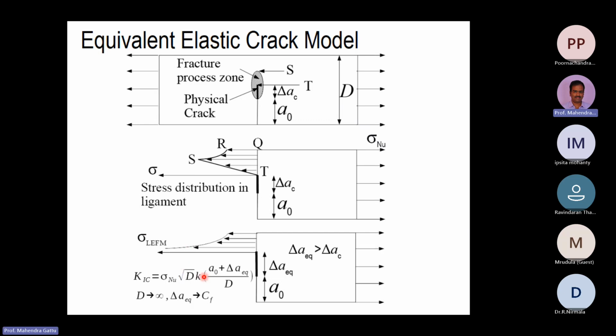So we have the structure size D here. As the structure size increases, and the structure becomes large, this delta A equivalent will approach one value called CF. CF is called the material characteristic length. For a very large structure, meaning an infinite size structure, delta A eq will stabilize and reach one critical value called CF. This will be a material property. For a very large size, the maximum possible fracture process zone you can develop is CF, and that is called the material characteristic length.